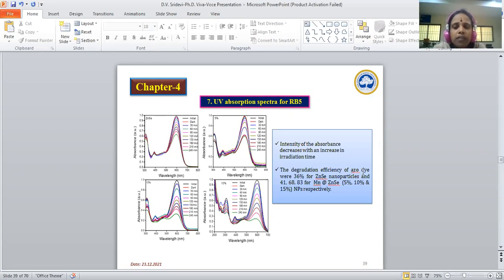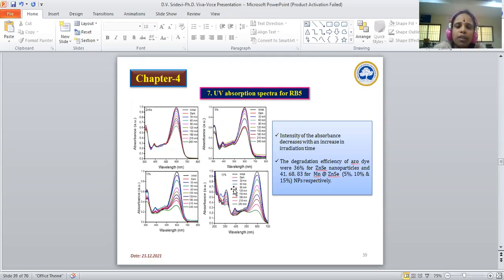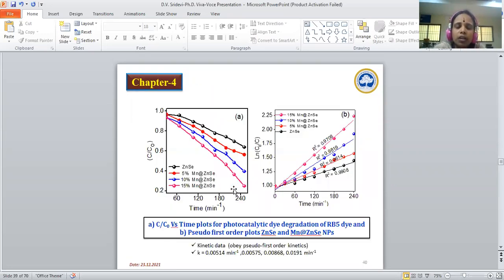The degradation efficiency of an azo dye was 36% for zinc selenide, and 41, 68, and 83% for 5, 10, and 15% manganese doped zinc selenide nanoparticles respectively. As a result, 15% manganese doped zinc selenide nanoparticles showed enhanced photocatalytic activity compared to pure zinc selenide, which is confirmed by plotting C/C0 versus time in min^-1 as shown in figure A.